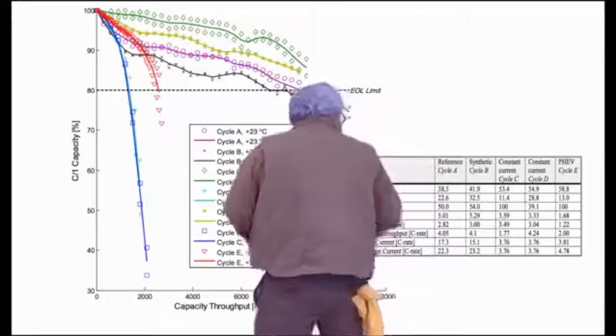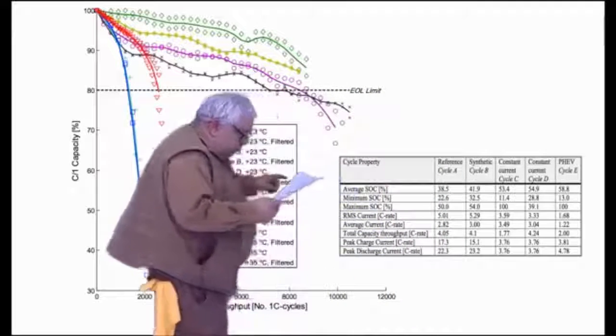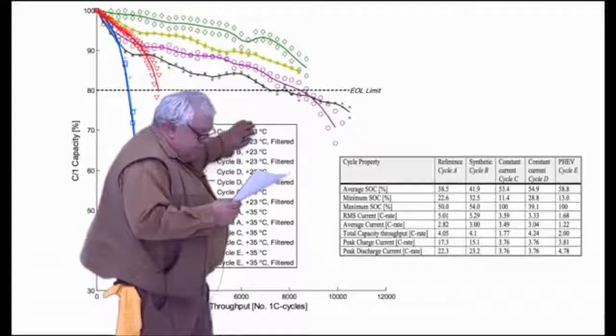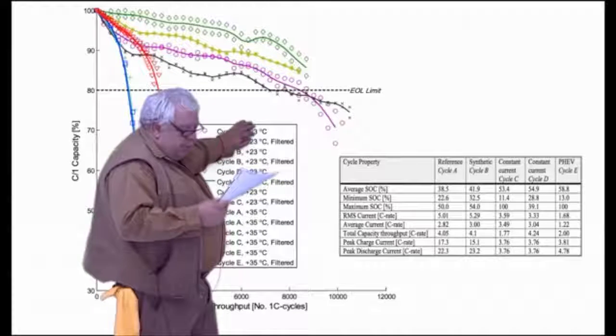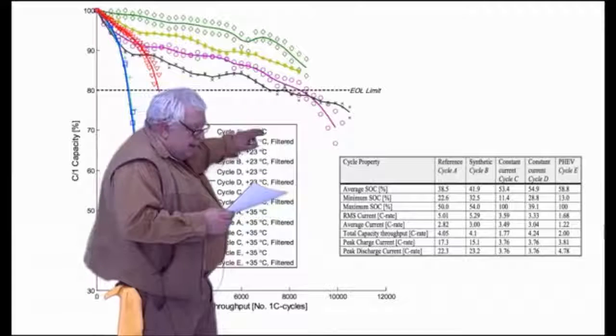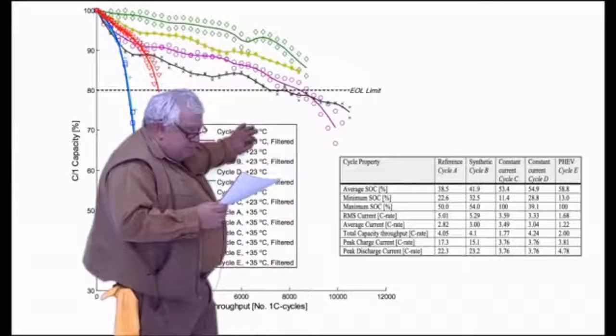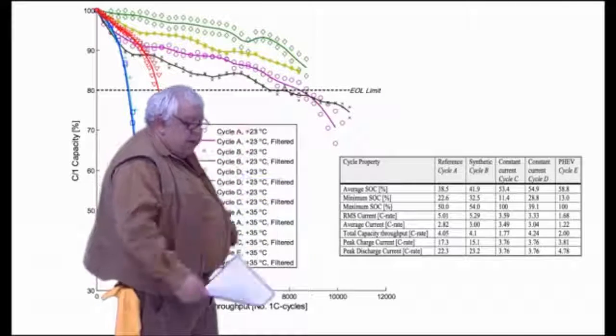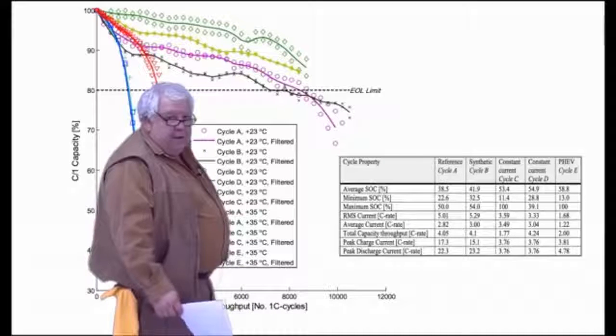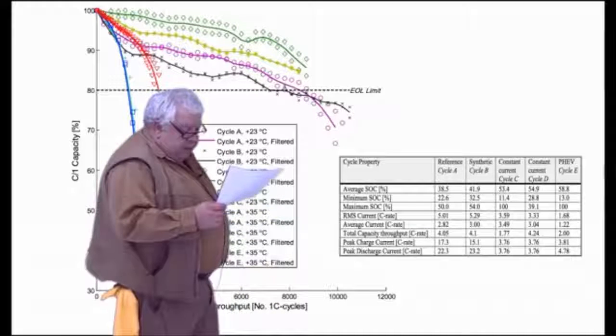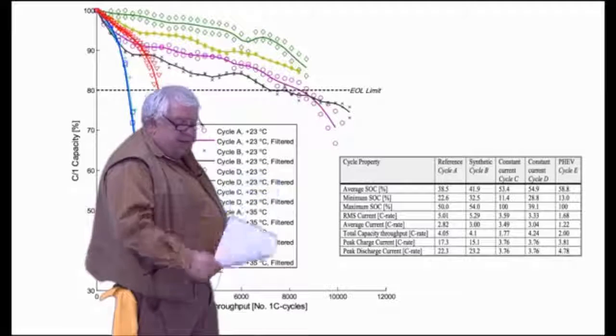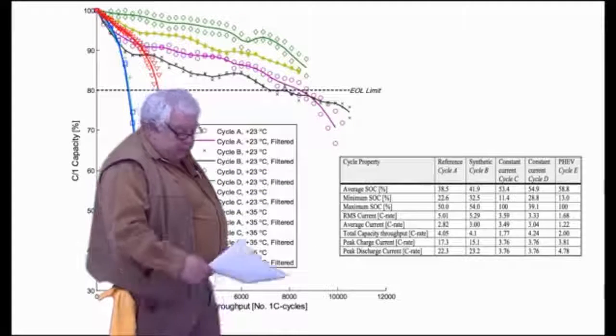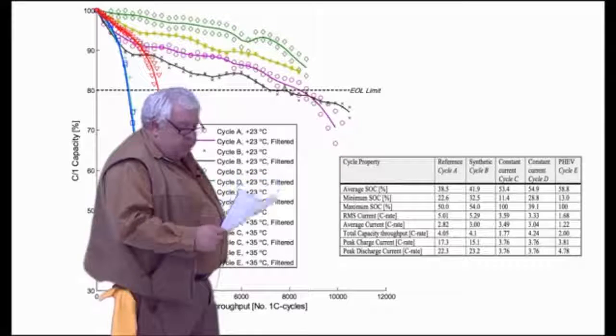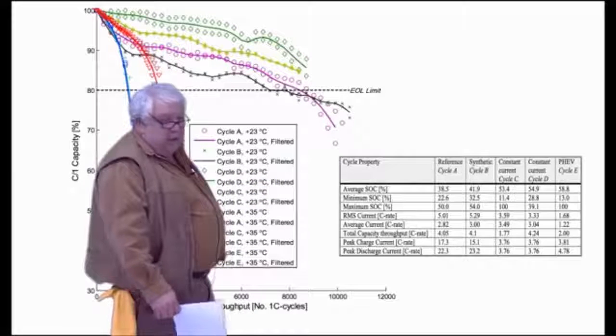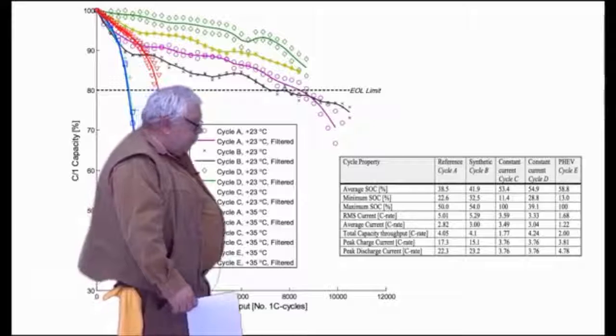Interesting to note of cycle A, and I've got it over here on this table, but cycle A only varied from 50% state of charge down to 22.6% state of charge, but included accelerations of this bus and regenerative braking. And the peak charge current was 17.3 C, and the peak discharge current was 22.3 C, which is a lot of current and a lot of strain on a cell.